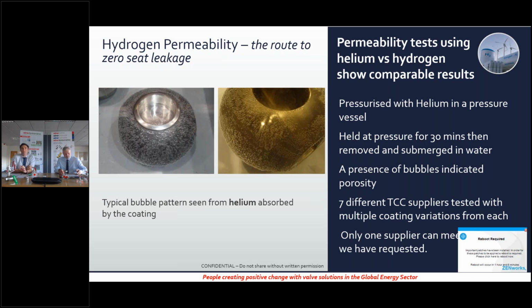Now, the first thing we needed to do is come up with an easy way of testing if the coating is porous or not. So the images you'll see on the screen there are from a ball that's actually failed our test. It has been pressurized in a pressure vessel for about 30 minutes using helium. It's then been taken out of the pressure vessel and put in a water bath. Now, any bubbles emitted from the surface indicate porosity. If you were to wipe your finger across those bubbles, they probably return within 5 or 6 minutes. Now, this poses a real difficult challenge because within a ball valve during a pressure test, you can't see if that porosity is actually through seat leakage or is just porosity.